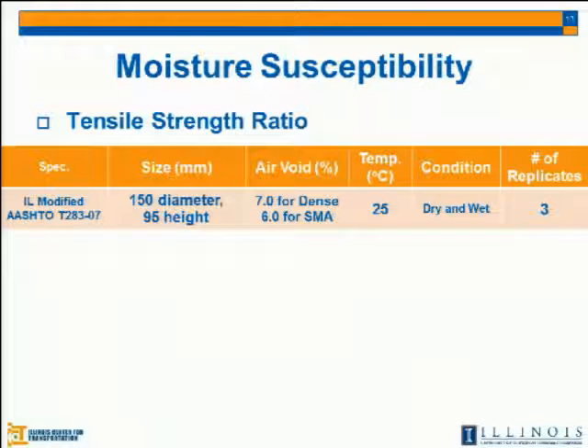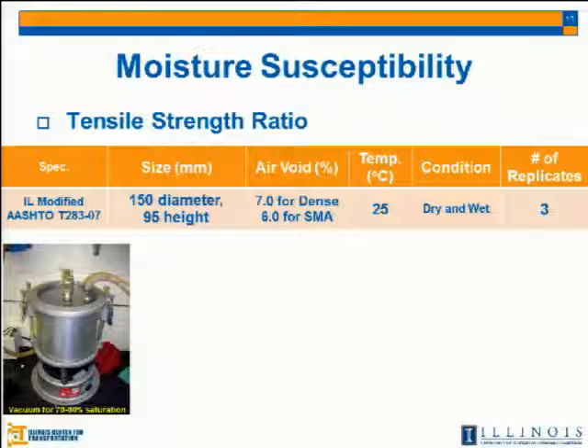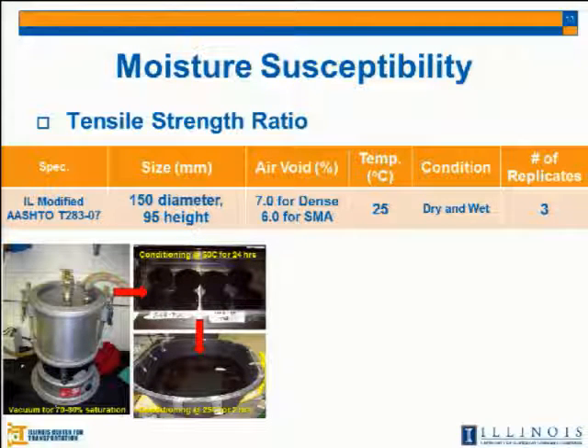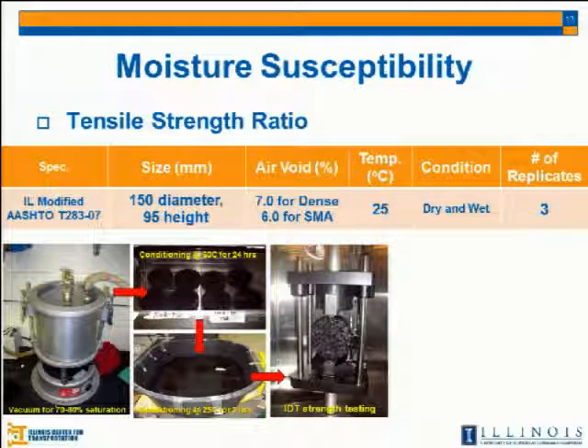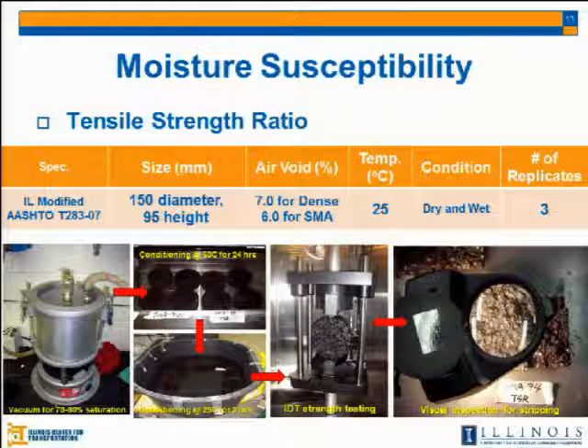The second one is the moisture susceptibility test. We did the TSR test according to the Illinois modified specification. For wet condition, after we make the gyratory samples, we saturate them to have 70 to 80% of the saturation level, and then condition them at 60 degrees C for 24 hours. After then, we put these samples in the 25 degrees C water bath for 2 hours, and then we conduct the IDT test. For dry condition, we just condition at 25 degrees C for 2 hours.